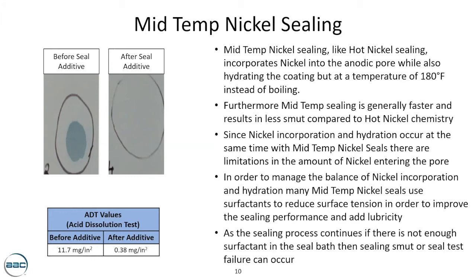So again, this is why the mid-temp nickel sealing is much more popular. You are getting a faster sealing, even though the surfactant is a challenge to manage. Now, when you make that surfactant addition, you'll see the huge drop in the ADT value to 0.38. So again, the critical element here is managing that seal additive, and by doing so, you optimize that trade-off between nickel incorporation and hydration.